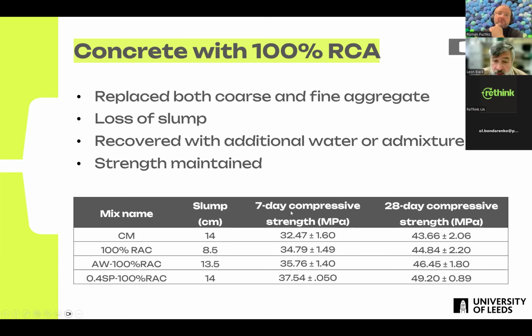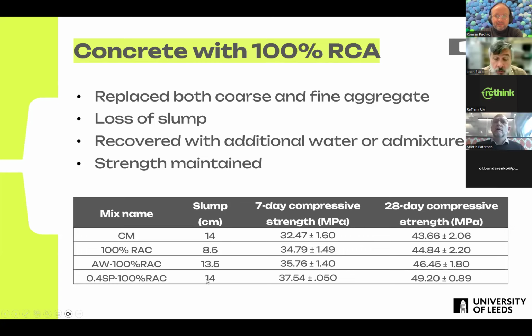When we compared the 7-day and the 28-day strength, we actually saw that by processing the aggregates, there was no significant loss in strength. Indeed, there was in some instances a slight increase in strength. But this is because the material that we'd used in Leeds was a rounded aggregate, and once it had been crushed, it became slightly more angular. That led to a slight increase in strength. So we were able to see that there really wasn't loss in performance. We could correct any loss in slump, and so we could make concrete that's comprising entirely of recycled aggregates.